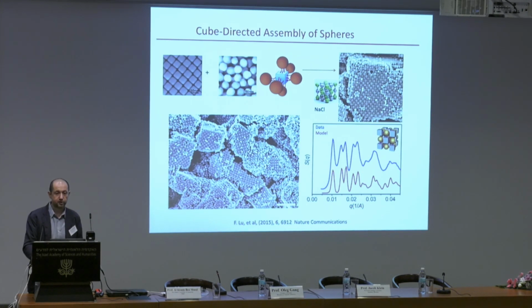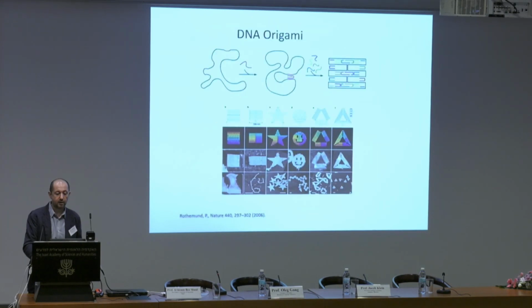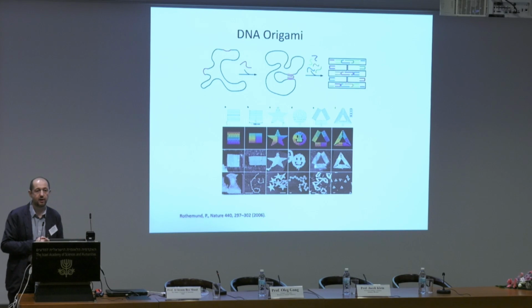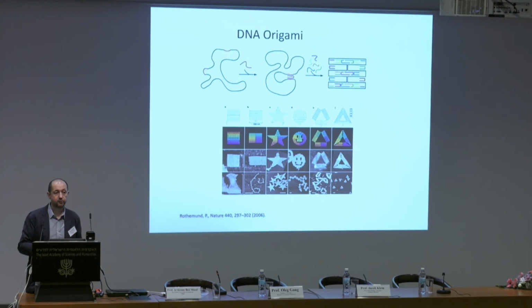However, if you want to generalize this type of approach, you very quickly realize you're limited in what type of shapes you can get from nanoparticles. So from this point of view, it's good to go back to the molecules. This is an approach which has been proposed by Paul Rothemund in 2006, DNA origami. For those who didn't hear about this, the idea is that if you take a very long DNA strand, in this case it's M13, close to 8,000 bases, essentially this strand is not just a polymer, but it has a very particular sequence. By providing, for example, staples which connect fragments which might be very far from each other from a linear point of view, but have the right addressability to be recognized by the staples, you can bring those fragments together. You can give, for example, 150 strands, and it allows to fold it. So Paul first demonstrated this approach for two-dimensional systems, but this approach also can be generalized now to 3 dimensions. So this allows to build structures out of DNA of desired shapes.